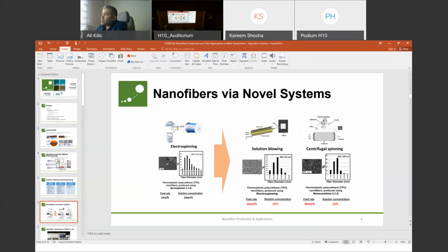So we do have a special type of spinneret here, and by means of centrifugal forces, we are forcing the polymer jet to form some fibers. These two systems are again fully mechanical systems. Even for the centrifugal spinning system, we were able to increase the productivity up to 30 milliliters per hour. This is just per nozzle; the comparison is done for only one nozzle.